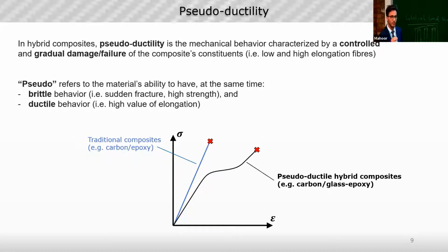keep some permanent deformation. But the fact in metals is that when metals are unloaded, they go back to the zero load level, and when they are reloaded they have the same elastic modulus. In composites, this doesn't happen, but this combination is called pseudo-ductility because we have damage, so we still have a brittle behavior inside. So the feature of composites is that they still show fractures inside and high strength. And the ductile behavior is that we can extend the deformation of composites up to a high value of elongation.